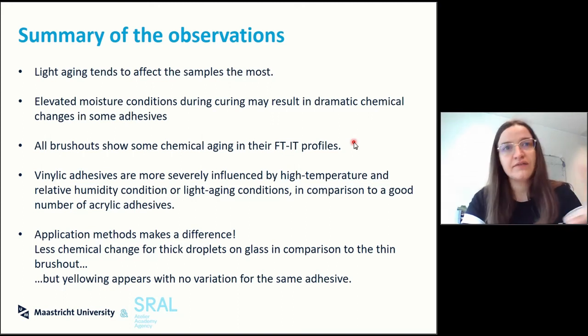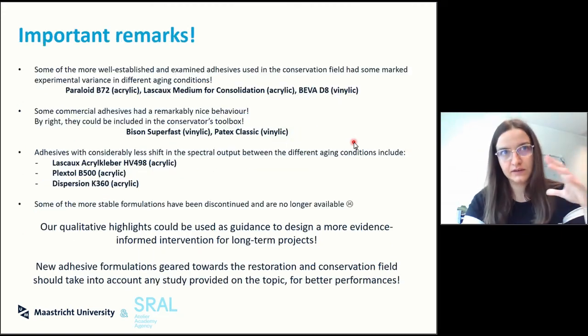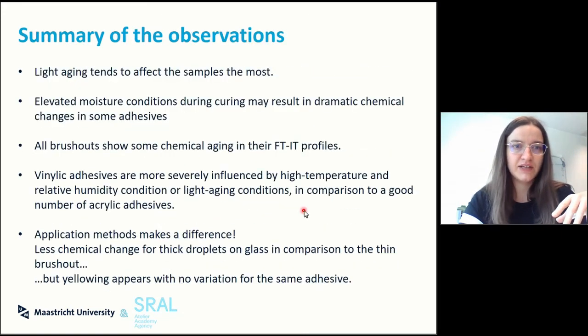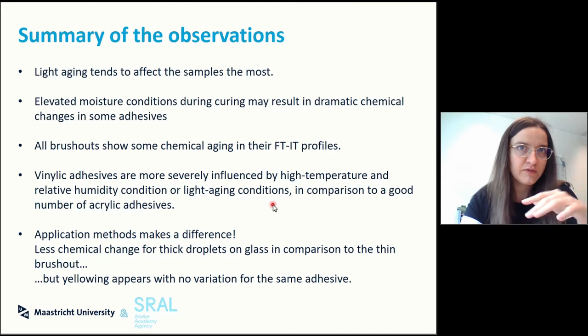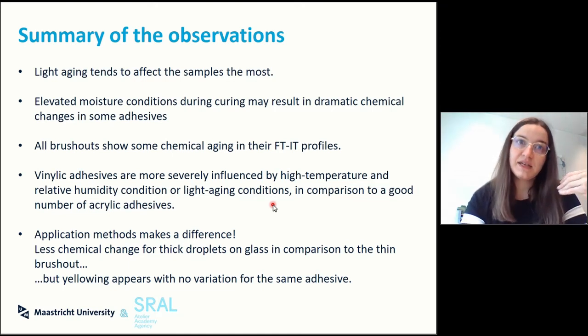All the brush outs have some chemical aging reflected in the FTIR profiles. In general, the trend is that if you use a vinylic adhesive, you have a more severe influence, especially in the high temperature and relative humidity conditions or light conditions, in comparison to a good number of acrylic adhesives, which, from the point of view of the FTIR, seem to be okay. And the application method does make a difference. So usually you see less chemical change when you have a very thick droplet on the glass in comparison to the thin brush out, but the yellowing will appear regardless of you putting a whole drop or you brushing out on the surface.